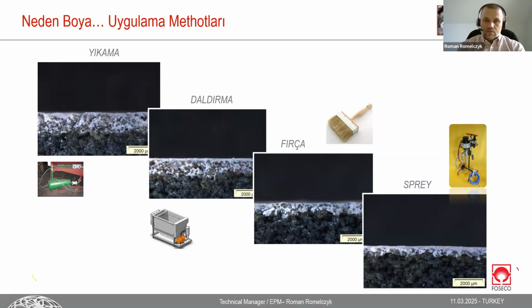So the best we can say, to prevent metal penetration or burning-on kind of defects, is of course the left side of the slide, where we have quite a nice penetration and the layer itself is also nicely built. When we talk about the right side, it's less penetrated, but the layer is also enough to prevent some kind of defects.